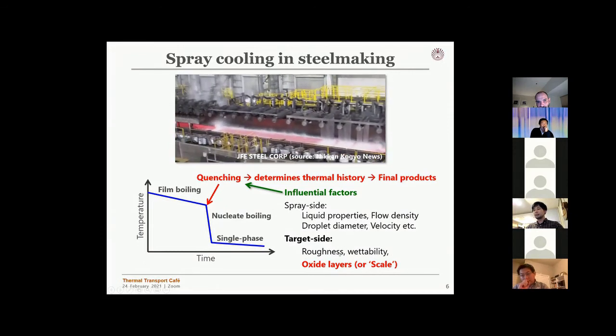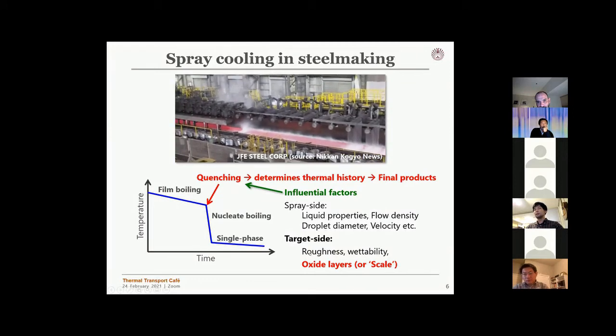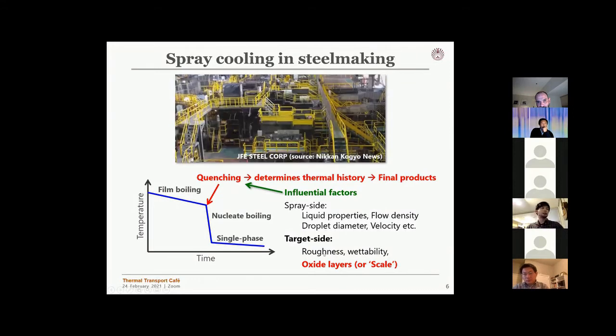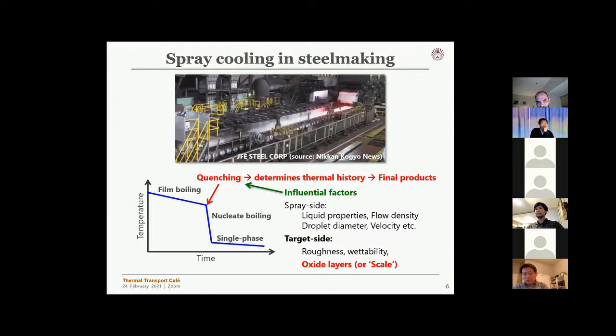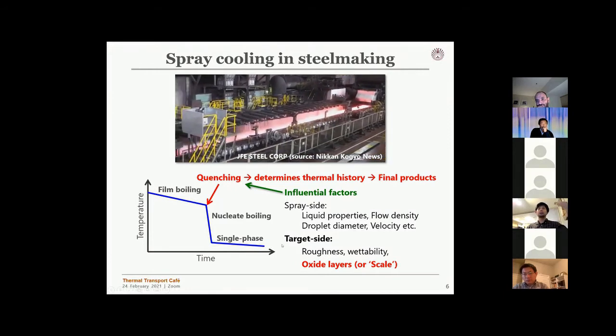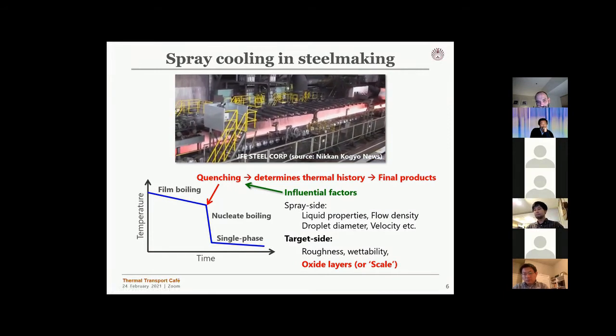So the surface roughness or wettability - if you have a rough surface and more wettable surface, you basically increase the quenching point. So you enhance the quenching, which has been known.